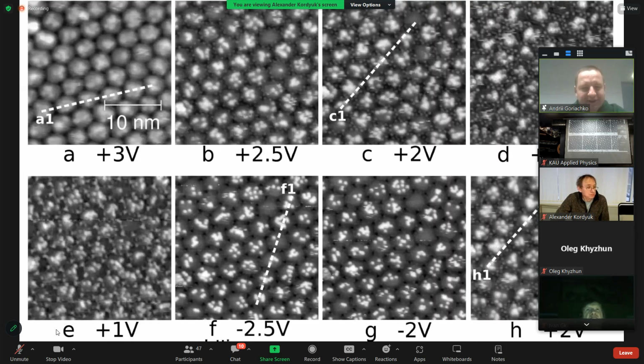Also, I have made experiments at different, although low, electron energies, that is, obtaining spectra in a scanning tunneling microscopy experiment or observation. And here we indeed have been able to confirm that, yes, the graphene layer can act as a sort of analogy to the grid of the vacuum triode.